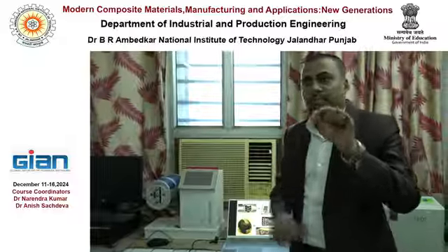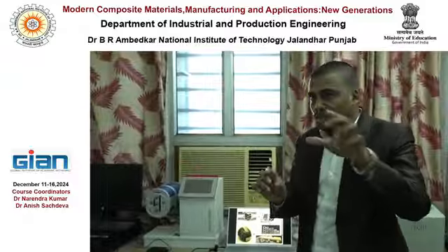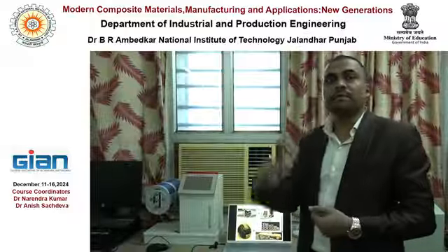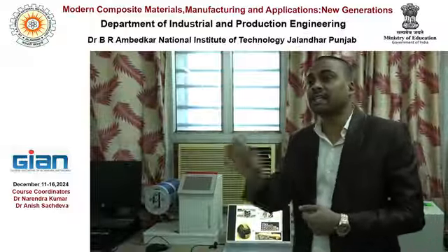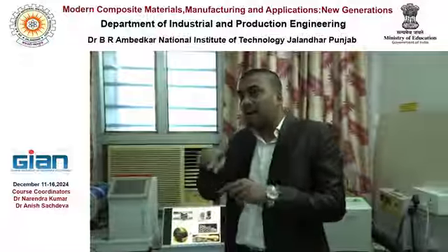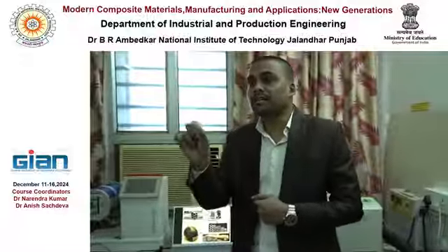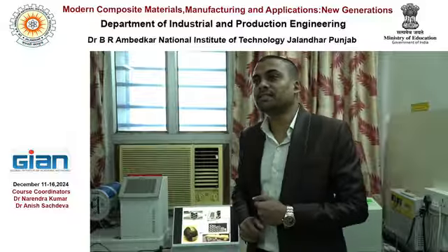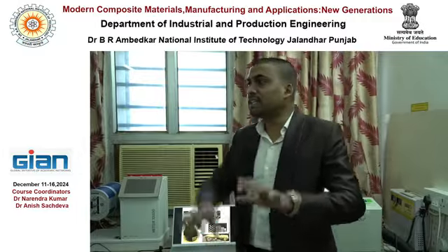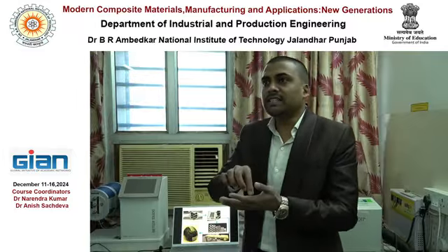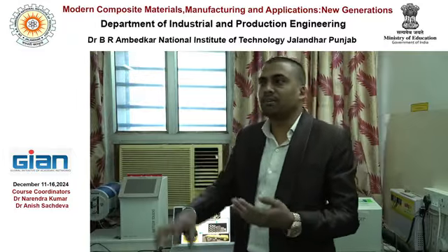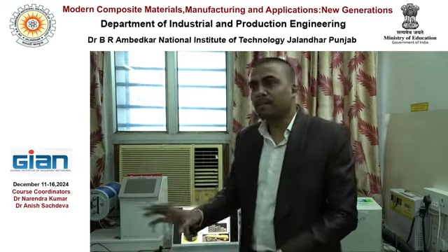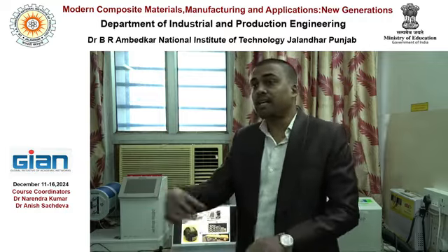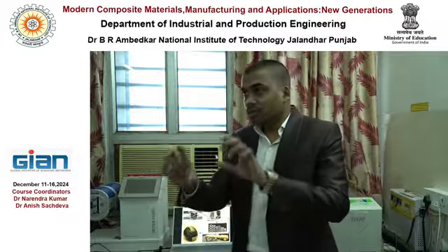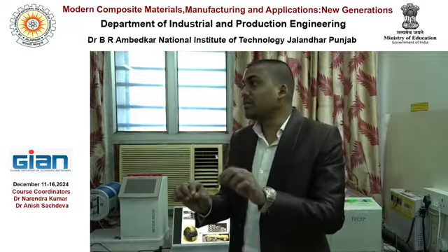You simply take the epoxy resin and the hardener in the proper proportion, mix it, and place it in a DSC. You will get a downward peak. That point is the curing temperature of that particular epoxy. People generally make a mistake: they take any epoxy resin, mix it, and simply cure it at any temperature given in a research paper. But that is wrong. You will not get good mechanical performance if you do that. You have to do DSC, then only you will get the correct curing temperature for this particular epoxy.